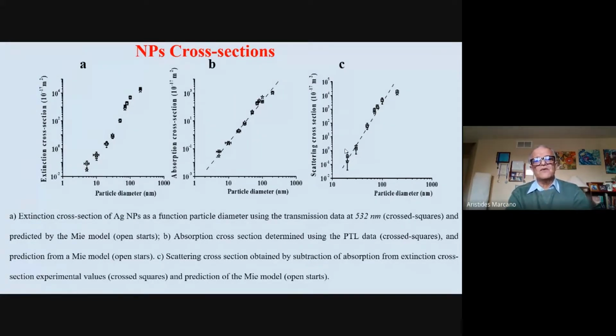Interesting thing, when you do photothermal lensing, you get this third order dependence, which is proportional to the volume. That's the dependence of the cross-section versus the diameter of the nanoparticle. You see this is third order, which means it is proportional to the volume. But for the scattering, it's proportional to the volume squared, as predicted by the basic theory of scattering. And you can actually see that the sixth order dependence on the dimensions means the scattering grows very, very fast when you increase the dimension of your nanoparticle.